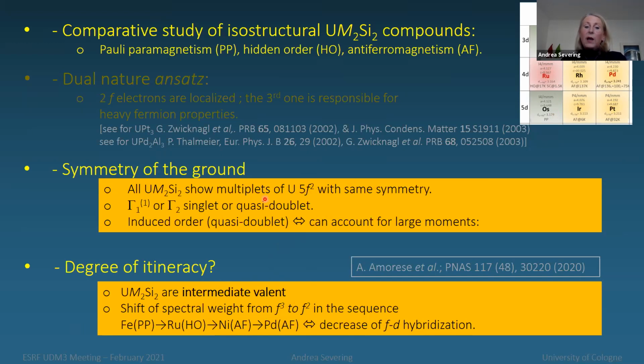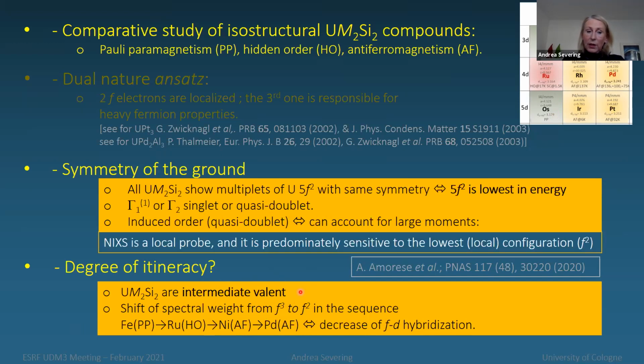You know, I wonder why I'm telling you that here we're seeing the uranium F2 symmetry, whereas I'm telling you the compounds are intermediate valent. Is this a contradiction? No, it is not. It is not a contradiction because NIXS, the non-resonant inelastic x-ray scattering, is like an x-ray absorption here at the O edge. So x-ray absorption, like for example the M edge, is actually sensitive to the lowest configuration. And this is here the F2. So in all compounds, the F2 is the lowest configuration, and that then couples with an F3 that is slightly higher in energy.